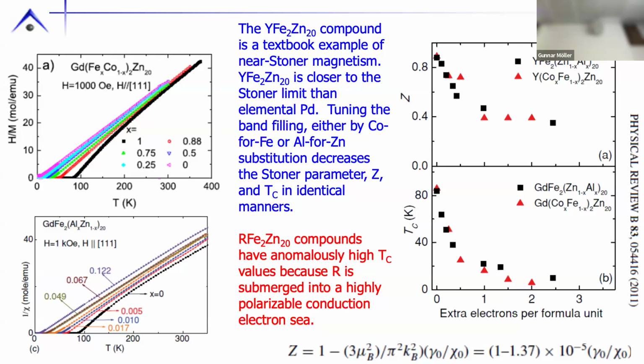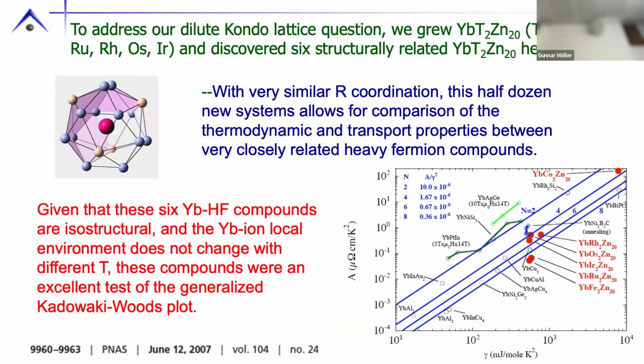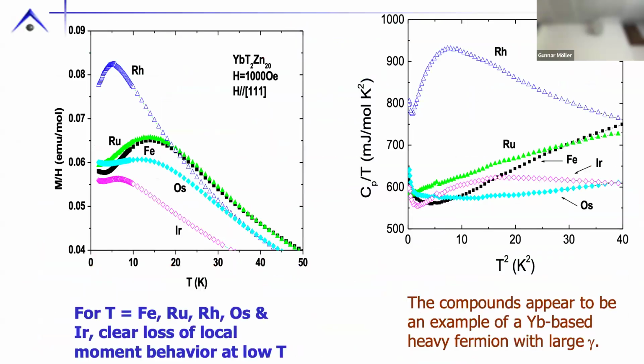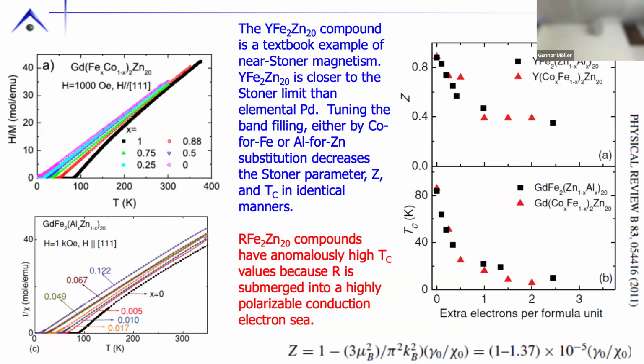Yeah, you have to be a little bit careful here. You have to be very careful with, for example, your susceptibility, because I have to get rid of the core diamagnetism. I'm looking at a small susceptibility. And this is just an experimental detail, but as a theorist, you might worry about it too. So I can figure out what the core diamagnetism for zinc, yttrium, and iron are just by going to the noble gas filled shell before that. When you do that correction, yes, it works very nicely.